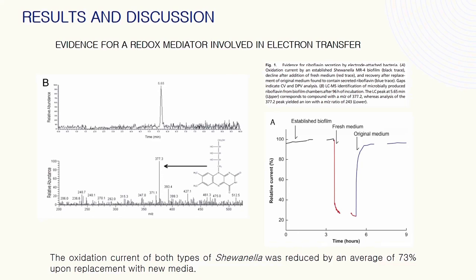Figure 1A shows an example of a typical medium replacement experiment for MR-4. The attached cells produced a soluble redox mediator capable of increasing the electron transfer rate to the electrode, as evidenced by repeated cycles of media replacement, a rapid decrease of 73%, and slow recovery. To investigate this hypothesis further, cell-free media from the electrode reactor were placed in sterile electrochemical cells containing identical glassy carbon electrodes and analyzed using linear sweep cyclic voltammetry.